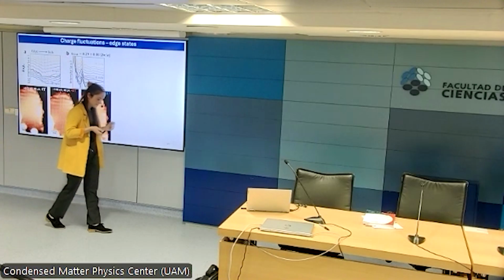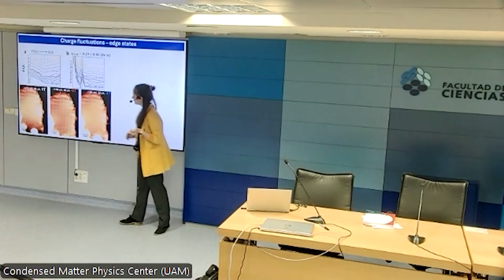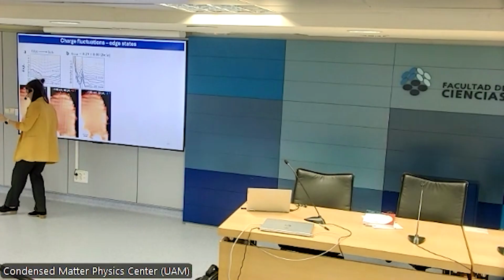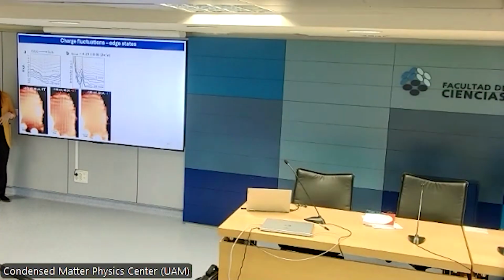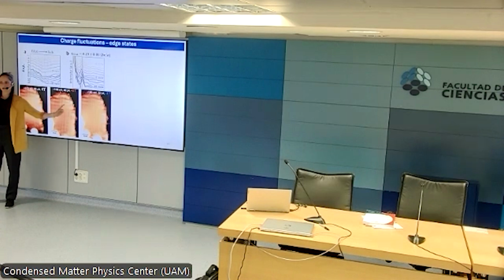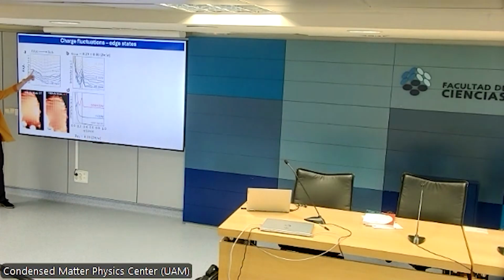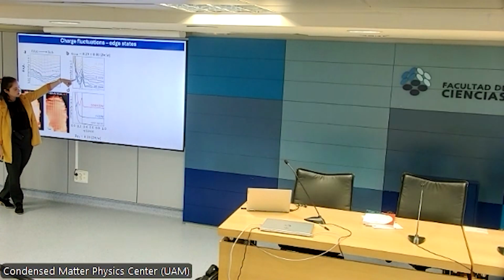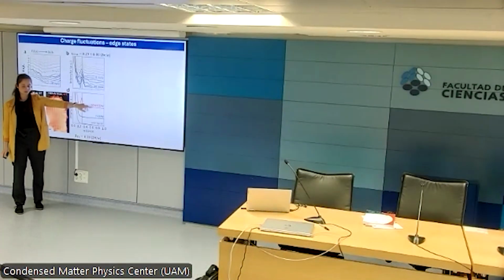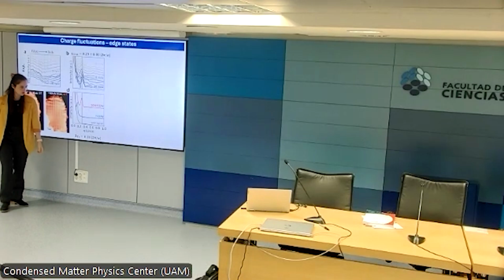The other very relevant piece of information that I have to give you is that I mentioned before time reversal symmetry breaking, preserving, and so on. The best thing to check this is to apply a magnetic field. This is the measurement done at 0 Tesla, and then we applied a magnetic field of 3 Tesla in the direction perpendicular to the plane, plus 3 Tesla and minus 3 Tesla, and you can see that the oscillation pattern is exactly the same, no matter what the magnetic field is. This is telling you that the symmetry was already broken to begin with. You are not breaking any symmetry here. And in fact, if you compare with theory, the frequency of the oscillations that we see matches pretty well the one that is predicted for the mixed spin density wave, charge density wave phase, which was 0.31 2π/a, whereas the one of the time reversal symmetry preserving case lies much further back.